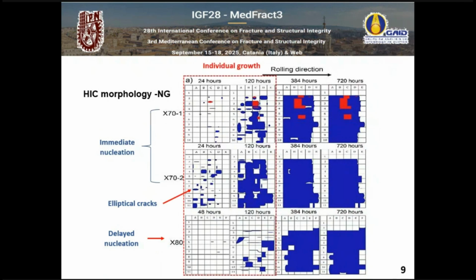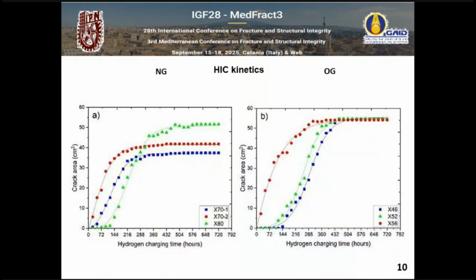And again, we observe the same individual growth stage and the interconnection stage. Now, here's the kinetics, and here's where the surprises begin. Because in the traditional fracture mechanics analysis, one of the most important commandments in our religion is that the cracks grow faster as they are larger, because the stress intensity factor is larger. That's the first commandment, or the second commandment, of fracture mechanics religion. But HIC just doesn't follow that.